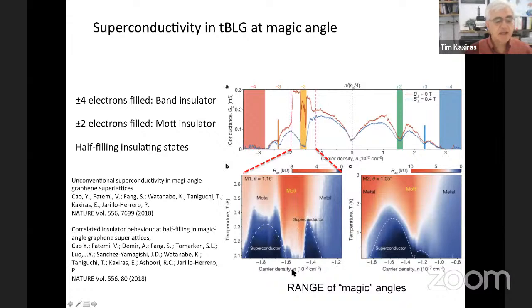This picture is very interesting, but what I want to point out is that superconductivity is observed at different values of the twist angle. So this value of the twist angle is 1.16 degrees. This value is 1.05 degrees. And again, you see a superconductor, but a slightly different phase diagram. And this is important because it tells you that there's a range of magic angles, not a unique magic angle. And I'll come back to this in a second.